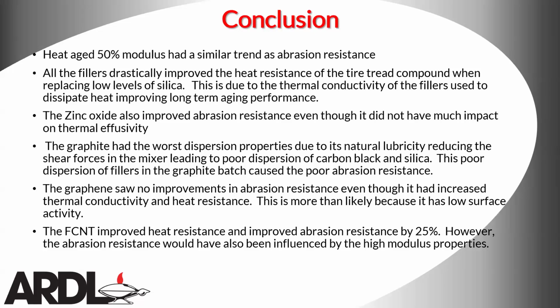The graphite had the worst dispersion properties due to its natural lubricity, reducing the shear forces in the mixer, leading to poor dispersion of carbon black and silica. This poor dispersion of fillers in the graphite batch caused the poor abrasion resistance. The graphene saw no improvements in abrasion resistance, even though it had increased thermal conductivity and heat resistance. This is more than likely because it has low surface activity or low polymer filler interaction.